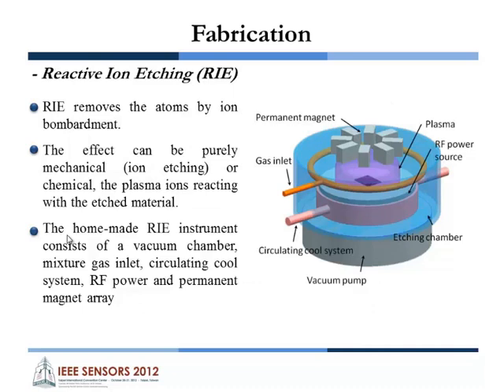Then a homemade RIE instrument was used to dry etch the metallic glass in this work. The principle of RIE is to remove the elements by ion bombardment. During the RIE process, the effect can be purely mechanical or chemical. Mechanical etching means ion etching, and chemical etching means the plasma ions react with the etching material. The homemade RIE instrument is shown here, and consists of a vacuum chamber, mixture gas inlet, circulating cooling system, RF power, and permanent magnet array.